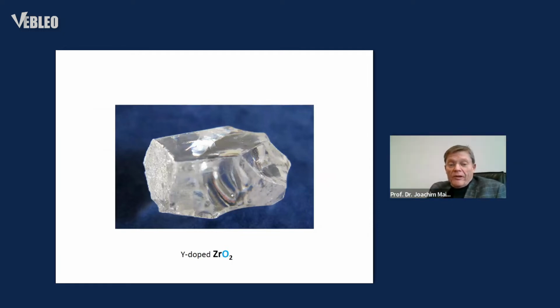This is a solid-state ion conductor, and this is zirconium oxide. It is appropriately doped such that the oxygen sublattice becomes mobile. You have a lot of vacancies in there. And at high temperatures, this crystal can be used as electrolyte for fuel cells, with the help of which you can convert hydrogen and oxygen to water electrochemically. But still, in spite of this, the crystal behaves like a solid, and it is a solid because the zirconium ions are very sluggish.